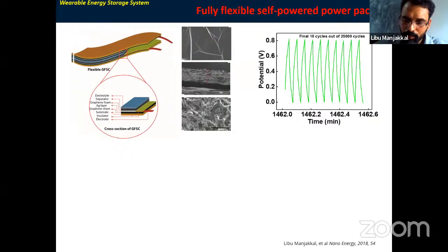Previously I developed sensors, but my major difficulty was how to power these sensors for continuous online monitoring. For example, in the daytime we can use solar cells or other energy harvesters. But during sleeping time, how do we monitor the sweat continuously? Then I started developing a flexible version of energy storage, initially with a graphene sheet. But the problem with a graphene sheet is that it is hydrophobic, and we need more electrolyte interaction and more energy storage. Then I started to develop this energy storage on a graphene foam.